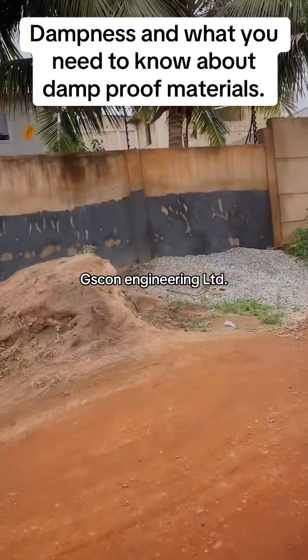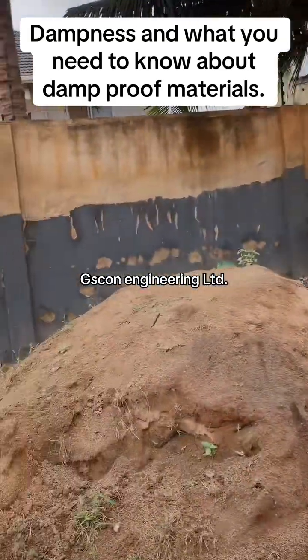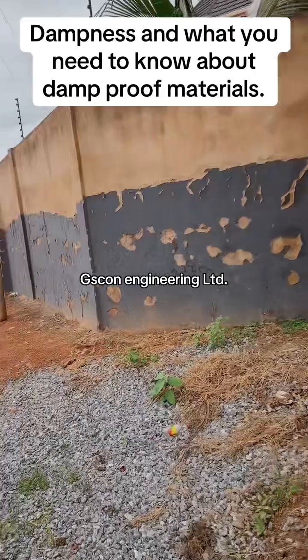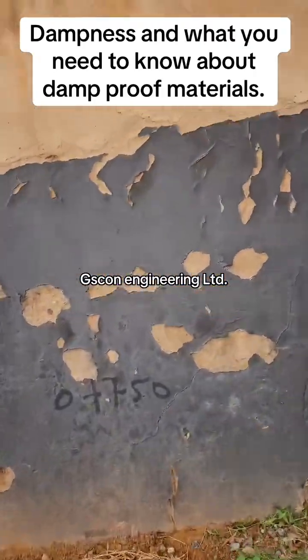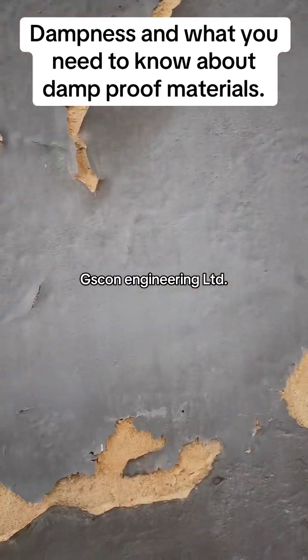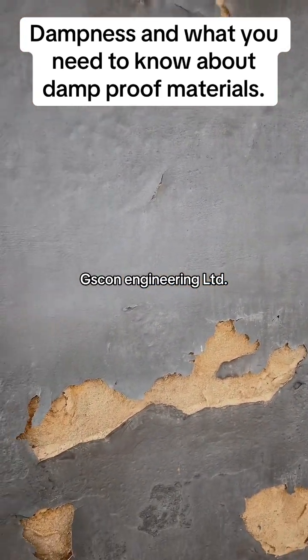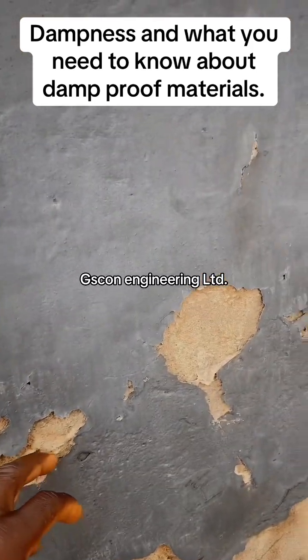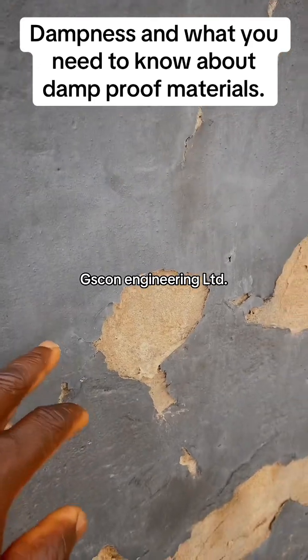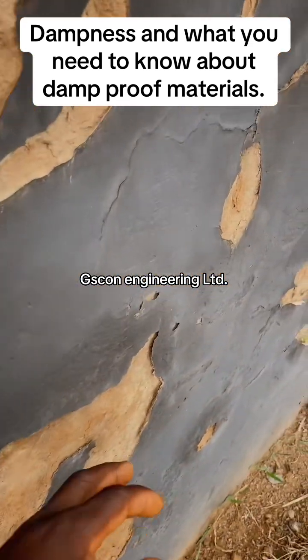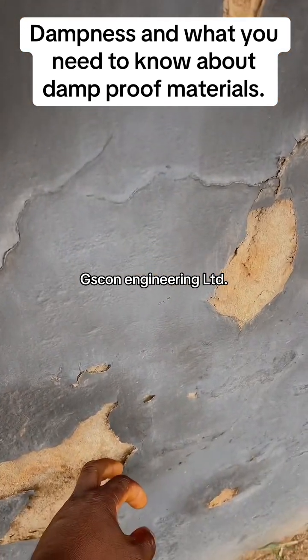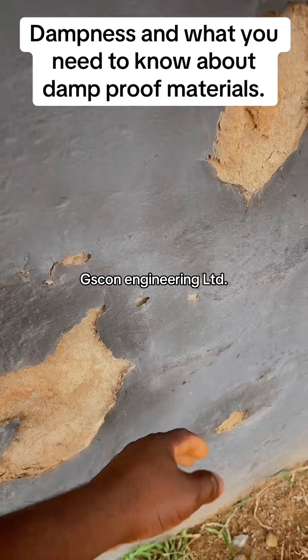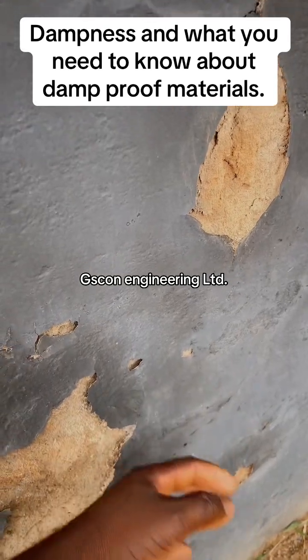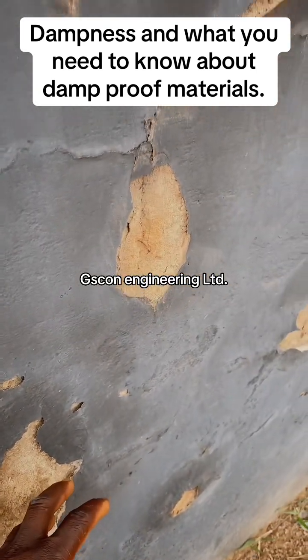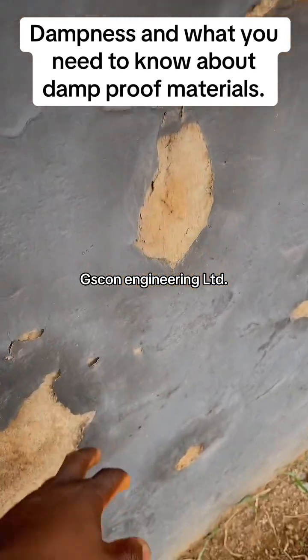So in most cases, that is why sometimes when you see people painting with this family of damp-proof materials, it will take time before blistering will start occurring. So this one has been painted. Afterwards, you can see that the blistering has started, and now the material will lose bond with the wall. In most of my past videos, I did mention that when you build a weak wall and you are thinking that you are painting some of these things, the wall is supposed to hold the bitumen. You can see that the whole thing is hollow. So it has lost bond with the wall, because the wall will blister. You get the point. When the wall blisters, it will lose bond with it.